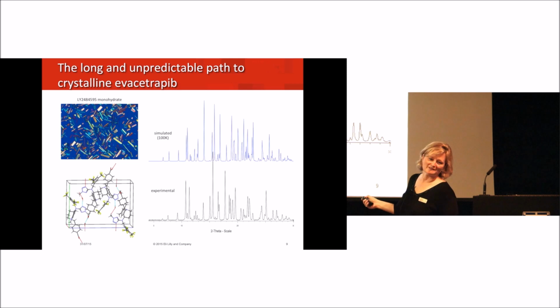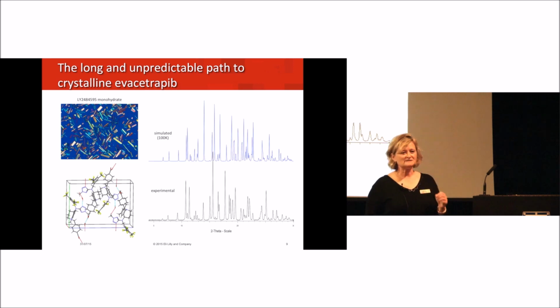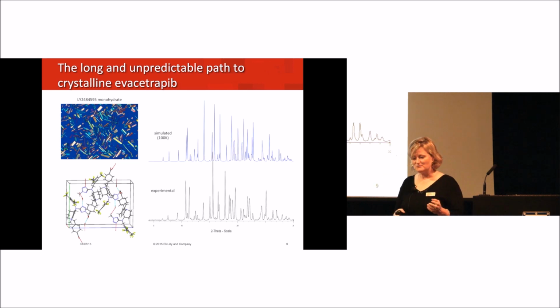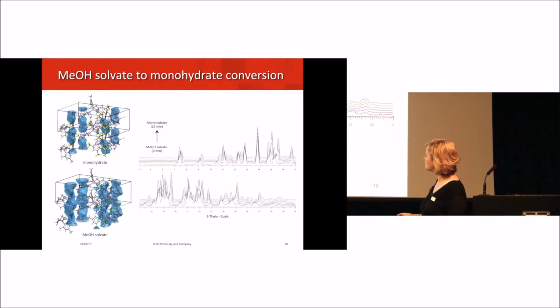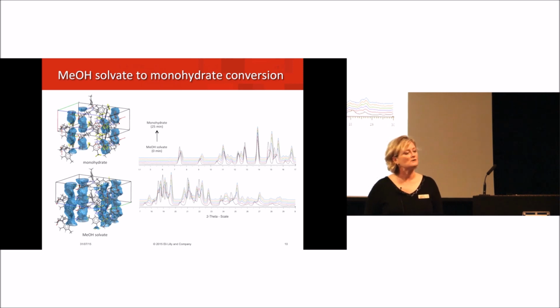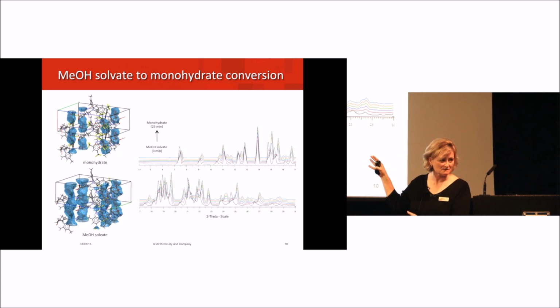And this is not what it first crystallized as. These are optimized, that's after optimization. But it crystallized in a failed attempt to make a formic acid solvate co-crystal. And it only crystallized then because we crystallized from methanol. And we're familiar with a lot of cases where failed salt and co-crystallization attempts yield a new form. But methanol was also important in this story because methanol was a precursor to this monohydrate crystal form that we finally obtained. And we had performed this crystallization many, many times on varying ranges of purity material.